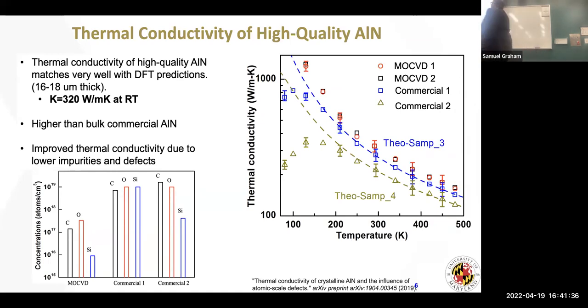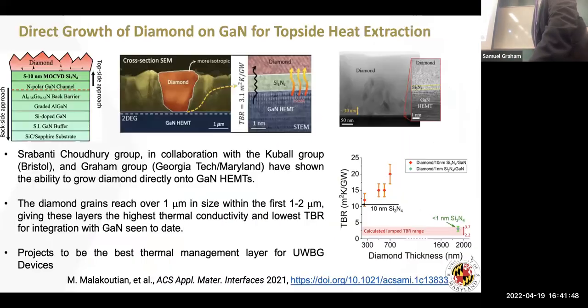So this is other things from the literature. This is the highest thermal conductivity aluminum nitride that follows the classical behavior of what you'd expect. So it says that, yes, we can grow these materials to the right thickness. We can grow them with high purity and high thermal conductivity. Here's another one that I'll quickly show.